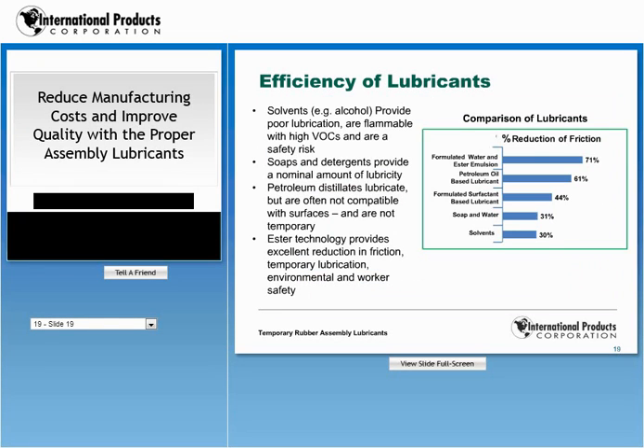Okay, here are some test results that we want to share that compares this ester technology with the traditional lubricants. So if you look at the chart on the right, the percent reduction of friction, you'll notice the top bar is 71%, and that's the formulated water and ester emulsion. And for example, if you have to install a tire onto a rim and it requires 100 pounds to do that without any lubricant, if you use one of these formulated ester emulsions, it reduces the friction by 71%, so that instead of using 100 pounds of force, you only need 29 pounds of force.